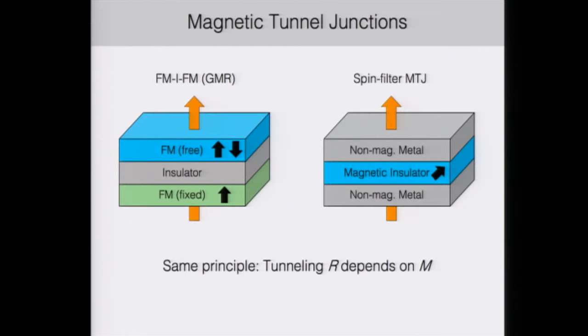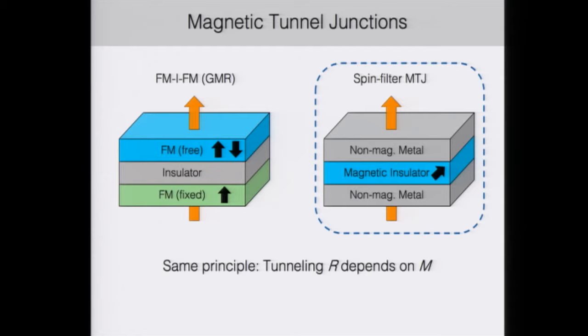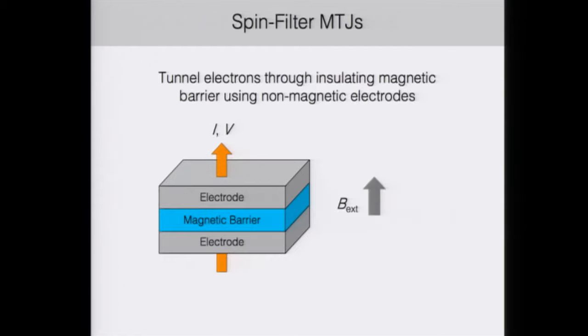So this GMR device is one geometry for a magnetic tunnel junction. But then there's also another geometry that you can imagine that has this same principle where the tunneling resistance depends on the magnetization. So in these spin filter magnetic tunnel junctions, you have two non-magnetic metals as the electrodes, but then the tunnel barrier itself is magnetic and can be changed. So since chromium iodide is a magnetic insulator, we wanted to take a look at these kinds of devices.